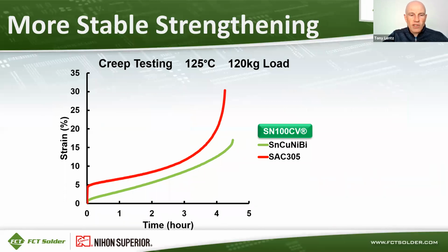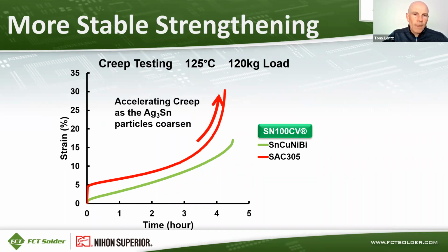Here's strain versus time in a creep test. And this creep test was done at 125 C with a 120 kilogram load. The red curve is SAC 305 and the green curve is SN100CV. The creep accelerates with the SAC 305 as the Ag3Sn particles coarsen, which happens between hours 3 and 4.